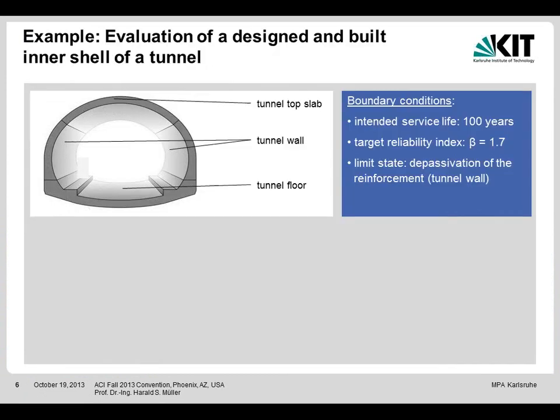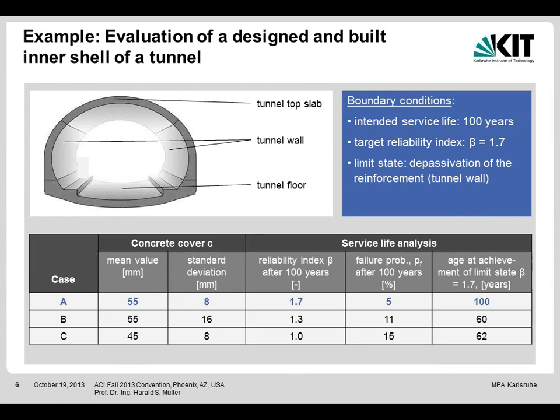Let me give you a very simple example. If you have, for example, a tunnel, with the top, the walls, and the floor, and the boundary conditions are that you will have a service life of 100 years. You accept 5% of damages, which means a reliability index of 1.7, and your limit state is a depassivation of the reinforcement. Then it was carried out, and if we now look, for example, just at the concrete cover, these were the design values: a mean cover of 55 millimeter and a standard deviation, which is unavoidable, of 8 millimeter.